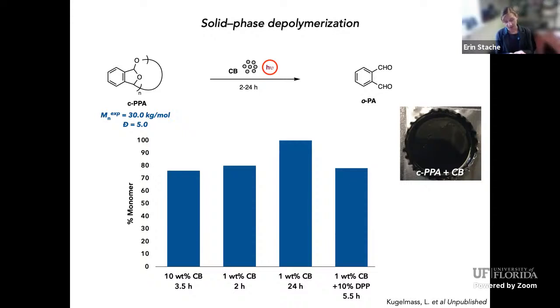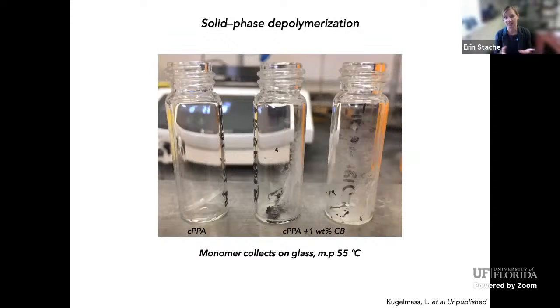Now, most commodity polymers are not pure polymer. They usually have other composites or plasticizer in them. And so Liat added some diphenyl phthalates, 10 weight %, and we still see pretty efficient depolymerization, albeit a little bit slower, but it still depolymerizes back to monomer very cleanly. And the control, if there is no carbon black, we don't see any depolymerization. Even though it's getting pretty hot inside of those vials, the films just look completely perfect, just like they did before we irradiated it with red light, suggesting that the photothermal effect is responsible for depolymerization.